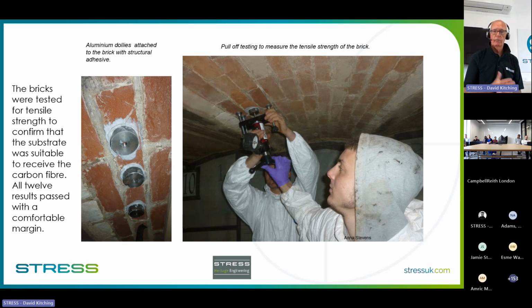So you do these tests, and for those of you who haven't seen, you bond these 50 mm diameter dollies to either concrete, or in this case brickwork obviously, and then when the adhesive is cured, you pull them off normal to the surface, and what you hopefully do is debond part of the brickwork. You want to see what that bond strength of the brickwork is, not the adhesive to the brickwork. It's actually hopefully pulling a little bit of brickwork away. Obviously, if it bonds well enough and the adhesive comes away from the brickwork and you've reached in excess of 1.25 newtons per millimeter squared, you've got no problems anyway. So this is part of the quality control.